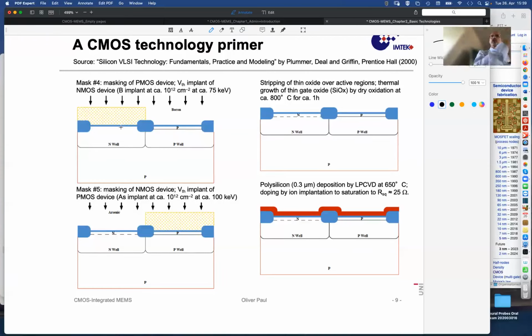But the oxides have all been grown. They were not deposited, they were grown from the silicon. And here we have, now I correct myself, the second real deposition step of this gate material, and the thickness of this gate. Maybe I should talk about thicknesses also here. This thickness is maybe 0.3 micrometer, 300 nanometers. And it's highly doped, as it says here, with phosphorus, P, to make it highly conductive.